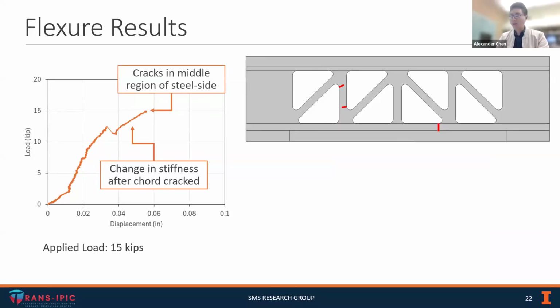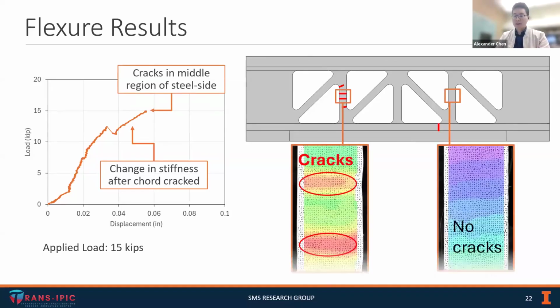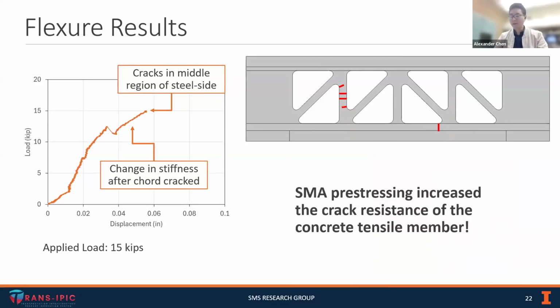And when we reached an applied load of 15 kips, we detected signs of cracking, this time 2 horizontal cracks at the middle region of that concrete tensile member reinforced with steel. Meanwhile, there are no cracks being detected at that middle region on the side that's been pre-stressed with SMAs. So we were able to conclude that the SMA pre-stressing was effective at increasing the crack resistance of the concrete tensile member.